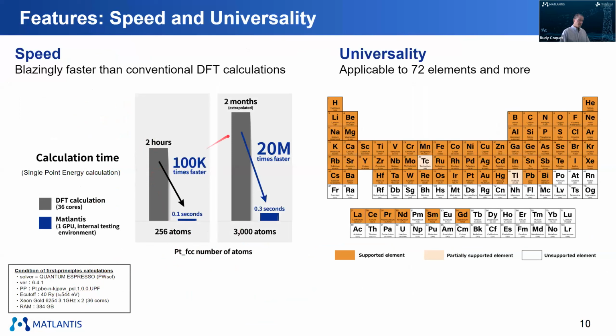More interesting is if you go up to 3,000 atoms, which becomes almost impossible for DFT, even using supercomputers, or it's very time-consuming. Matlantis will only take a fraction of a second again to do a single point energy calculation. Universality is the second very important feature, because you can apply Matlantis to 72 elements, and this is something that we are improving. So you see, it can actually treat the most important elements for most of our customers, including transition metals and those that are needed today for topics such as catalysis or semiconductor.